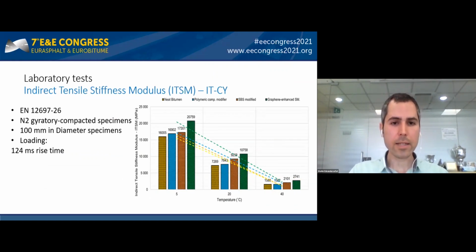We continue with the lab scale test results. The first test was indirect tensile stiffness modulus, done according to the European standard EN 12697-26. The test was done at 3 levels of temperature, 5, 20, and 40, representing low, medium, and high temperature, respectively. According to this plot, you can see that thanks to the presence of this graphene enhanced super modifier, the stiffness modulus of the mixture at all 3 levels of tested temperature was higher.